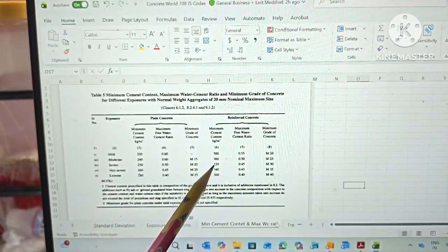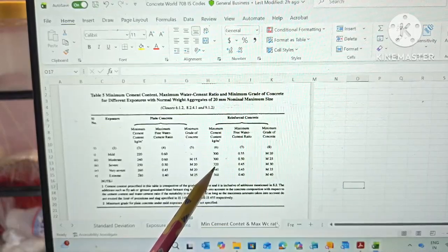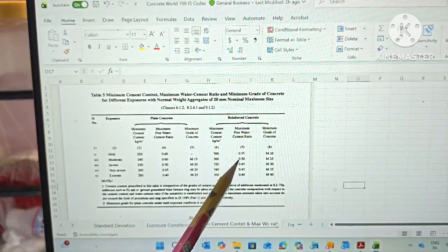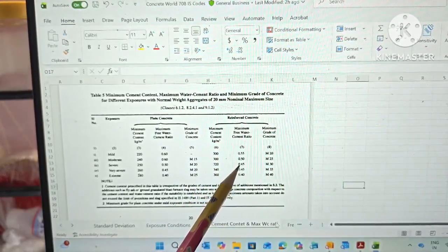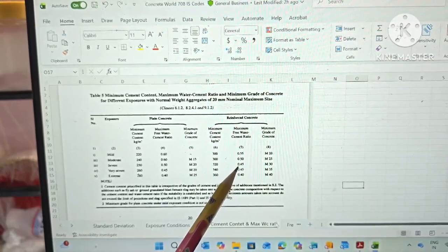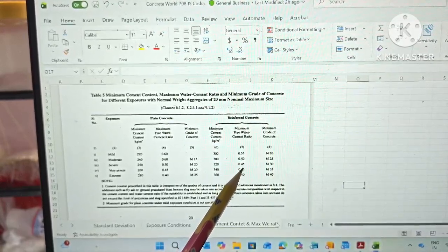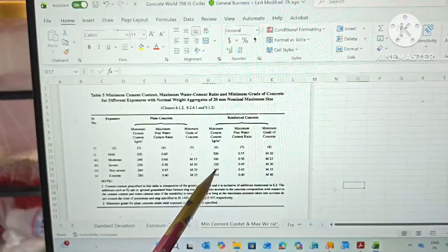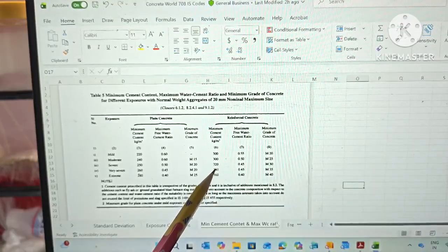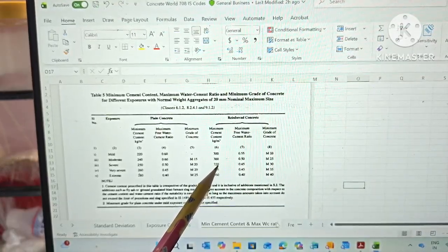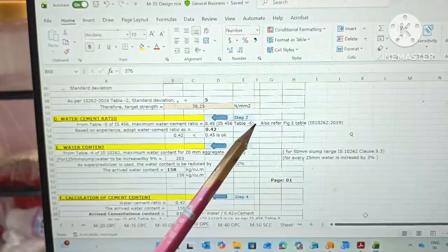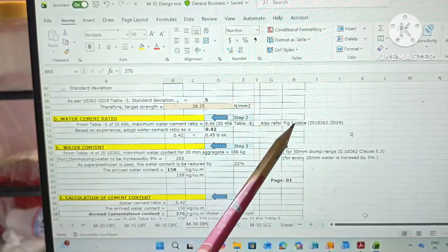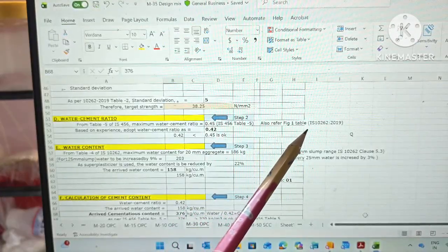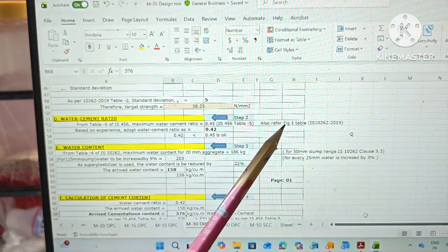So the minimum cement required for severe condition is 320 kg, and the maximum water cement ratio is 0.45. It means our water cement ratio cannot go more than 0.45, and our cement cannot be less than 320 kg per meter cube. So let's move to the calculation again. Also refer to Figure 1 of IS 10262:2019. So let's go to Figure 1.